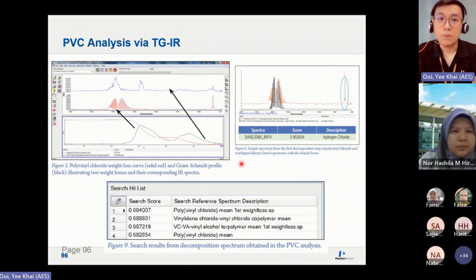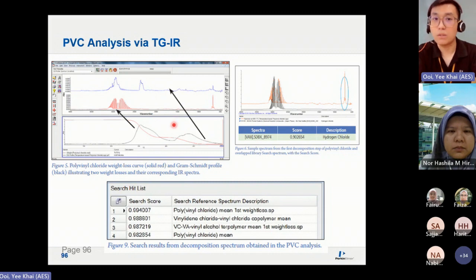For example, this is running a PVC material using TG-IR. PVC is polyvinyl chloride, so the side chain is hydrogen chloride. This is coming from the TGA, so the first weight loss, second weight loss. The black curve is what we call a Gram-Schmidt plot. Each of the points that you see is a spectrum from the IR scan. Correspondingly, we take the highest point for the first decomposition, and the highest point for the second decomposition, then we extract out the spectrum. The first spectrum, after matching with the library, tells you that it's hydrogen chloride, which is from the decomposition of the chloride side chain of PVC. And then you have your main chain break off of the polyvinyl, with a matching score of 0.99 against the IR library. So now we can see this is where the polymer breaks off, and this is where the side chain evolves. You get your identification together with the percentage of each component within the material.